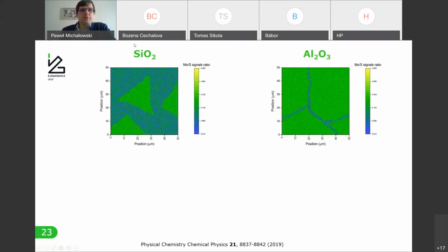So when it was silicon dioxide, based on the reference sample, we found that a molybdenum to sulfur signals ratio of about 4.4, a little bit below, represented in green, is a high quality, high stoichiometry MoS2. Everything else is not. So first, you can see that for silicon oxide, we can see some triangular shaped regions where there is a high quality MoS2, whereas for sapphire, these domains with a high quality material are much, much higher. However, in both cases, there are also regions where the stoichiometry is significantly altered.